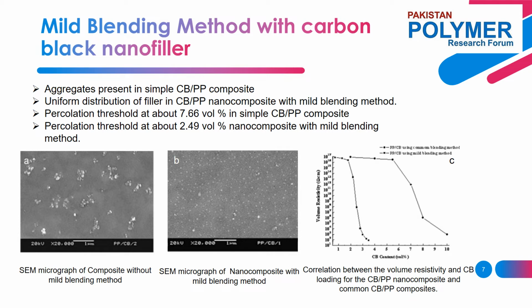This change in percolation threshold between the two carbon black and PP composites could be explained in light of the dispersion and distribution of carbon black particles. Conductive networks form in the common composite at high loading of carbon black due to the close contact of aggregates. The percolation threshold at lower loading of carbon black in the nanocomposite prepared by the mild blending method could be explained by the tunneling conductivity mechanism. In the carbon black and PP nanocomposite, the carbon particles were dispersed as primary particles, located apart from each other and enclosed by the PP, which is an excellent insulator. This arrangement satisfies the requirement of tunneling conduction.